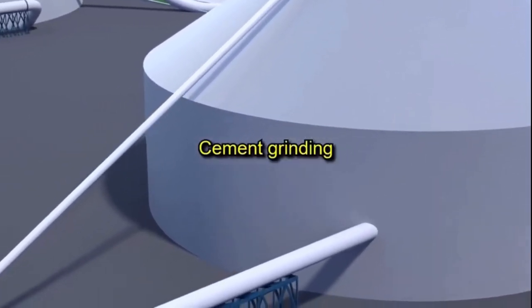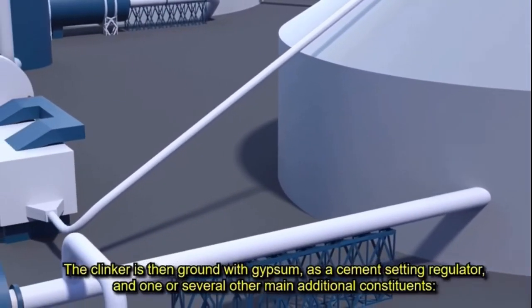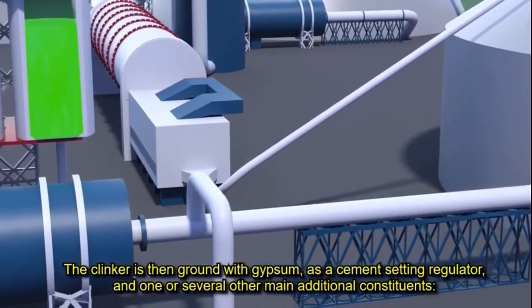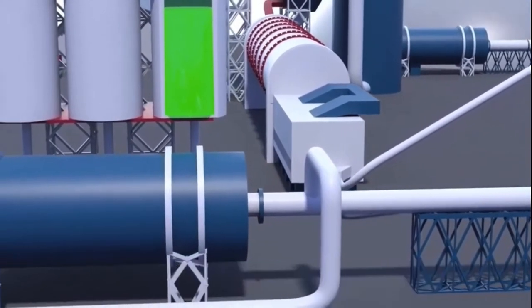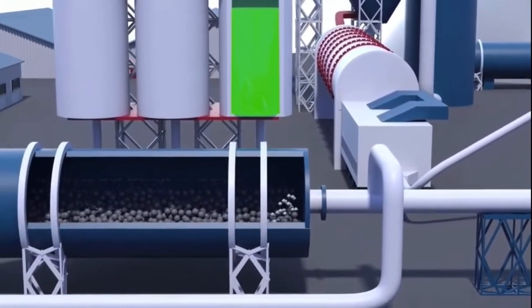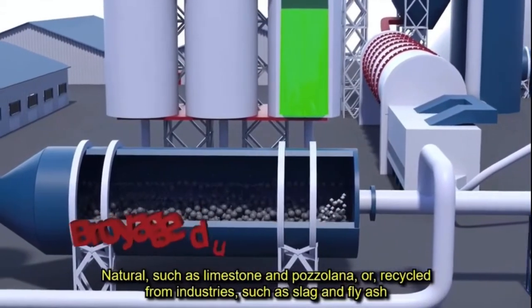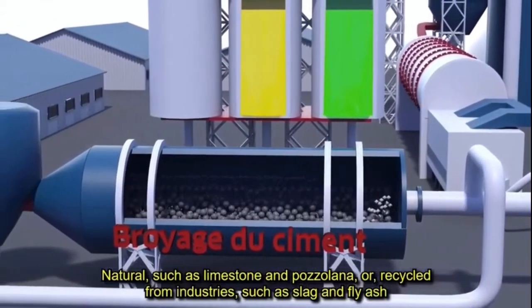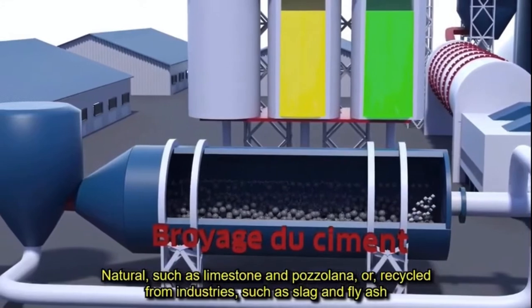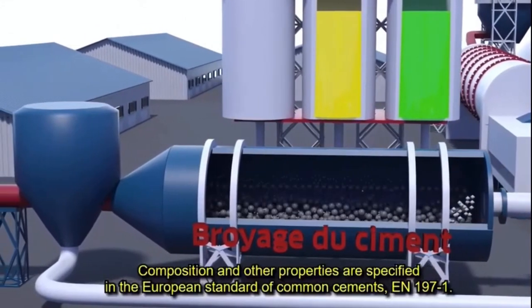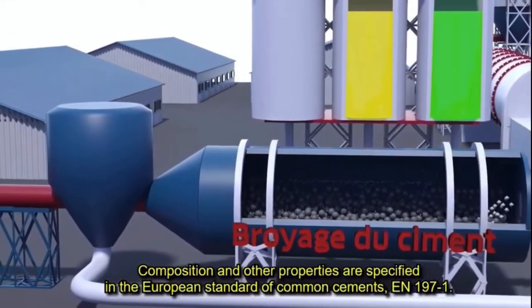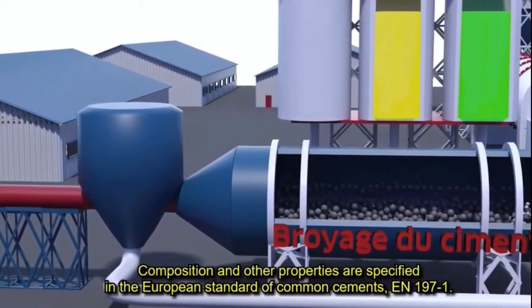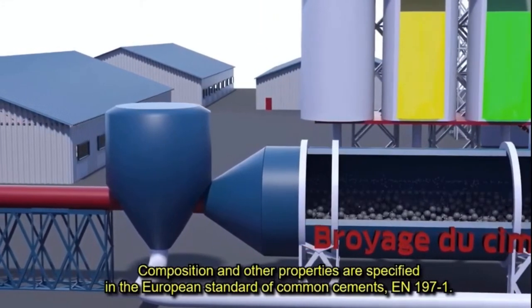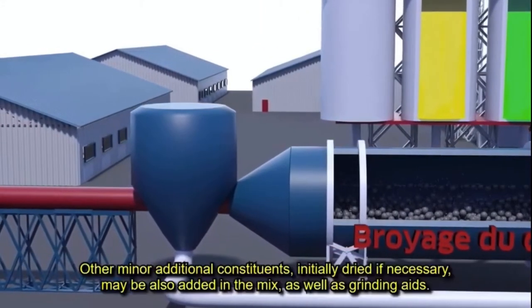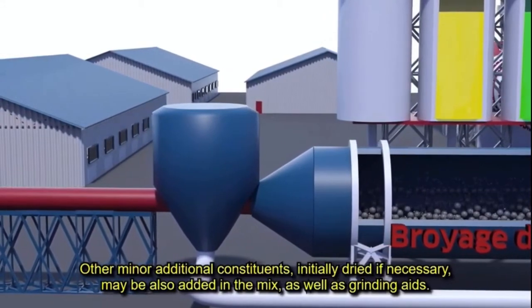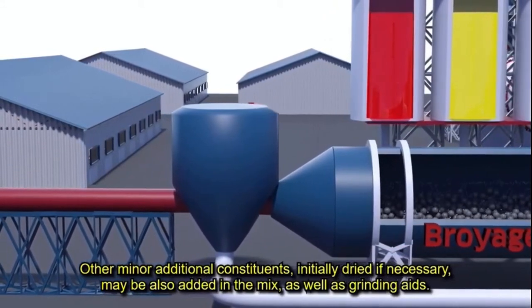Cement grinding. The clinker is then ground with gypsum as a cement setting regulator and one or several other main additional constituents, natural, such as limestone and pozzolana, or recycled from industries such as slag and fly ash. Composition and other properties are specified in the European Standard of Common Cement EN 197-1. Other minor additional constituents may be added to the mix as well as grinding aids.